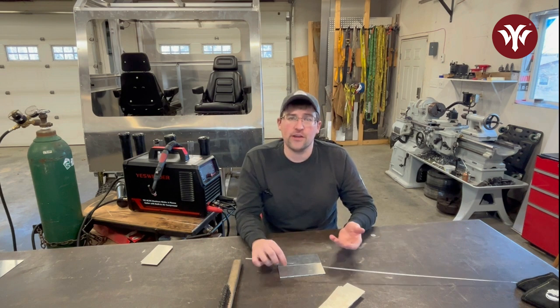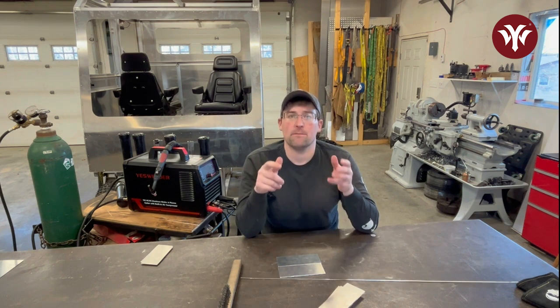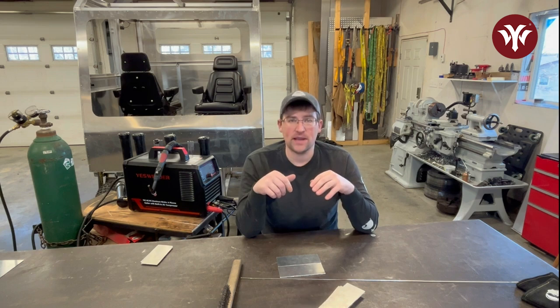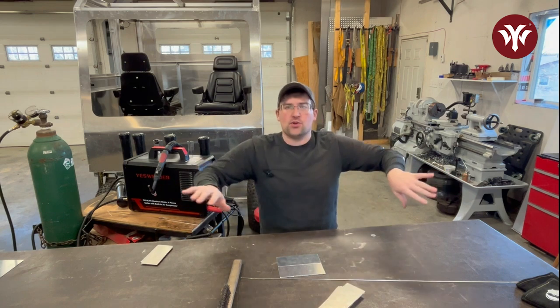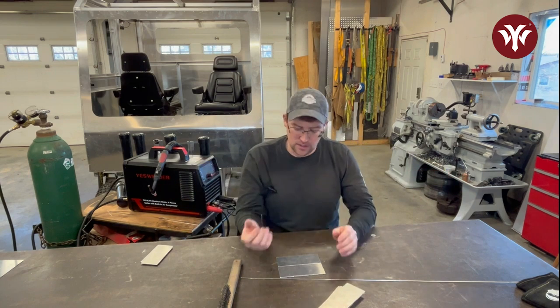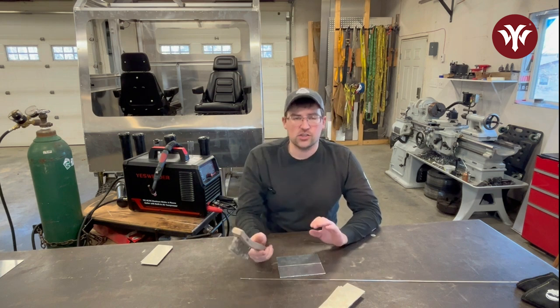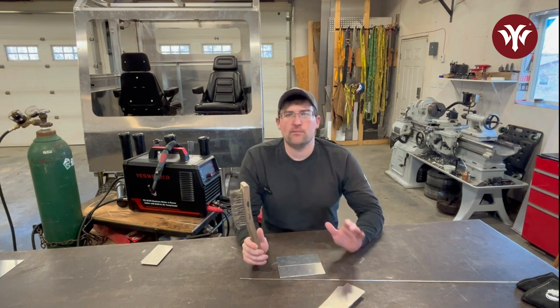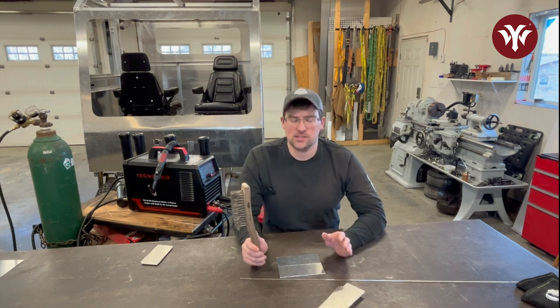And what can happen on thinner metals is you're trying to heat it up to get a puddle formed, and the actual base metal heats up so much that it just drops right out and you'll be left with a big crater. So what I always suggest if you're doing anything with aluminum, just keep remembering clean, clean, and clean. I can't stress that enough.